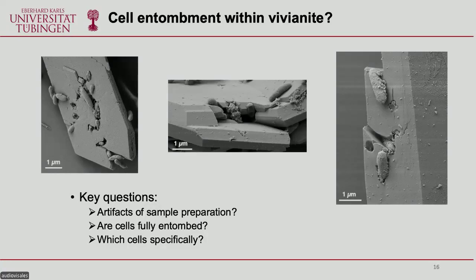But when we saw this, we were like, oh, okay, that's great, that's amazing, but we were also very skeptical, because we know that when we prepare the samples for scanning electron microscopy, we had to do a lot of steps in between, centrifugation steps, and this might cause some artifacts in the imaging. And so could this be just an artifact of sample preparation? And are the cells fully entombed or not? Or are they just partially covered?